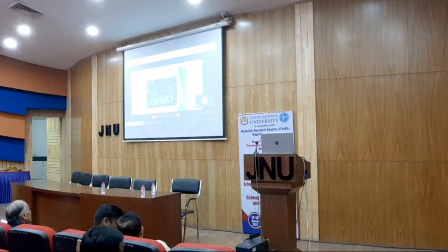These are the figures of FESEM. This is the image of 1 weight percent MnO2 MoO3 thick films fired at 450 degrees Celsius for 30 minutes. The thick films all consist of coarse and a wide range of randomly distributed grains with a size of 400 nanometer, distributed as smaller grains. The appearance of the film is porous, which supports the adsorption desorption type of gas sensing mechanism. These nanoscale grains exhibit a high surface to volume ratio.